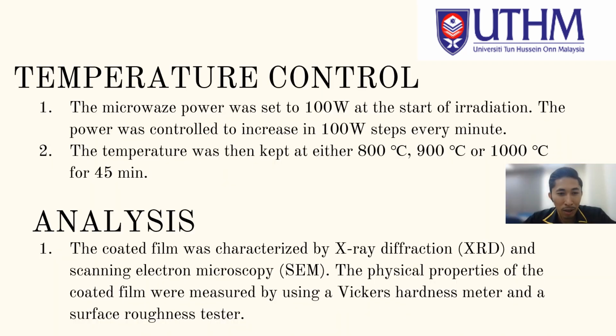Temperature control. The microwave power was set to 100 watts at the start of irradiation. The power was controlled to increase in 100 watt steps every minute. The temperature was then kept at either 800 degrees Celsius, 900 degrees Celsius, or 1000 degrees Celsius for 45 minutes.